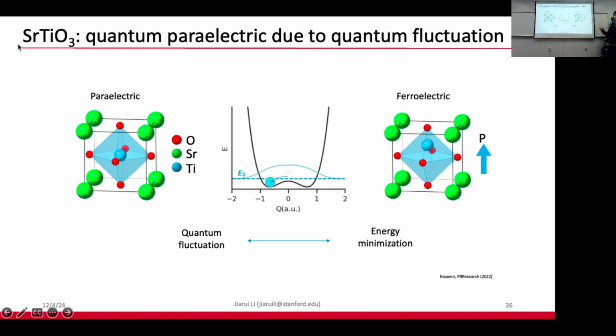If you are stretching away, then instead of changing the mass, the quantum fluctuation or the zero point energy should be roughly the same, or changing as the curvature changes. I'm just guessing maybe the strain doesn't make strong contributions to this quantum fluctuation, since it's mainly governed by the atomic mass. Right, because there are people trying to use isotope replacement of the titanium atoms, and they do see it changes, suppressing the quantum fluctuations. So it is related to the mass of the atom.